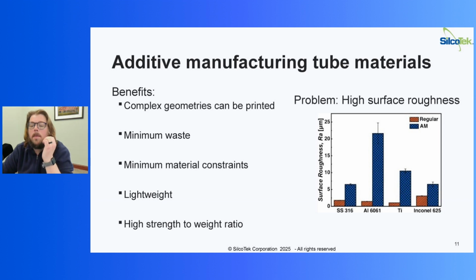One of the big problems, however, is when you 3D print these various materials into these tube shapes, they have a really, really high surface roughness. So you can see on the right-hand side, just the 316 stainless steel, aluminum, titanium, Inconel. Every single 3D printed tube has a higher surface roughness.